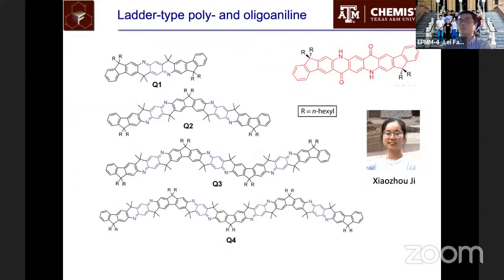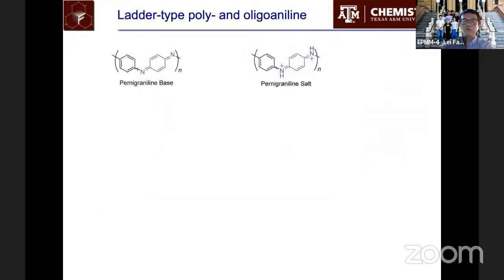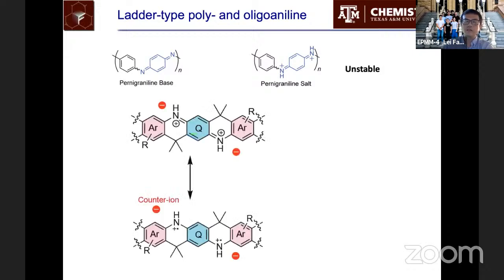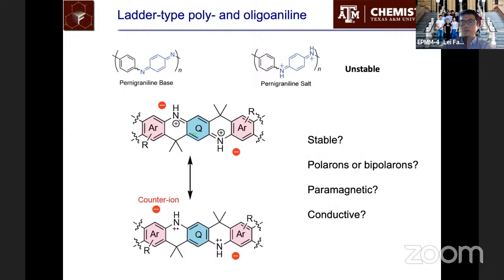So, moving on. We are also interested in making polyaniline derivatives of ladder polymers. We all know that polyaniline, a widely used conductive polymer, can have different redox states, change color, and also be conductive when you acid dope it in an oxidized state. But polyaniline has a problem: if you fully protonate it and oxidize it, it becomes unstable. So very little is known about the intrinsic property of this fully oxidized and protonated state of polyaniline, so-called pernigraniline. And here we can make a ladder-type or few-strand analog of polyaniline, which will give us good stability and also allows us to study their electronic and magnetic properties.